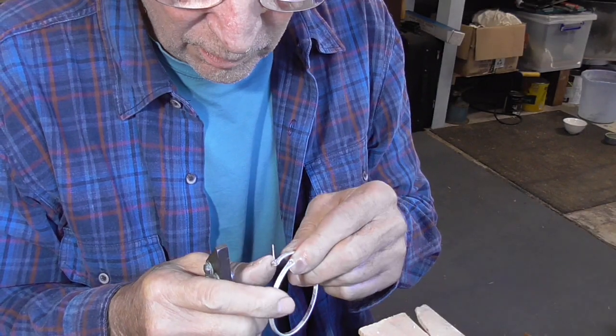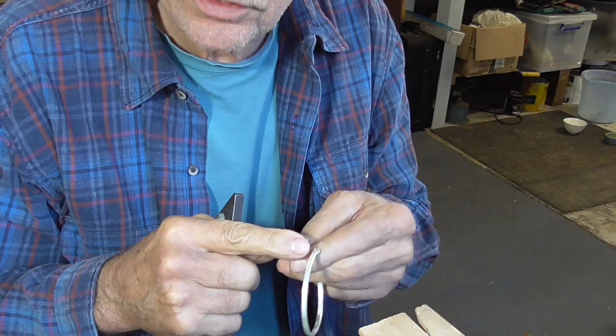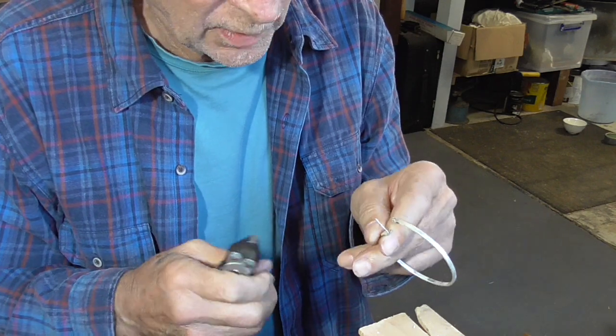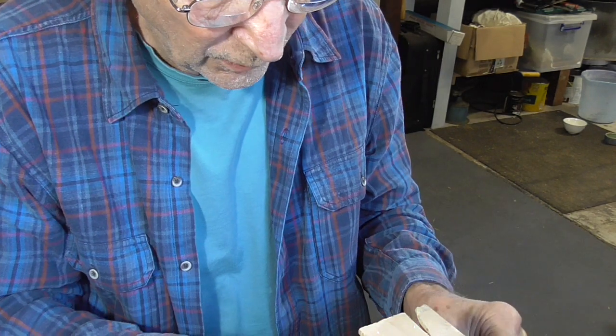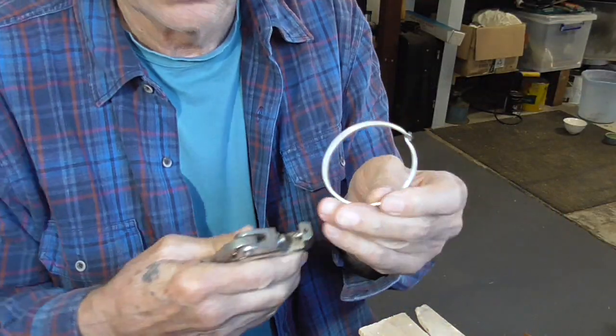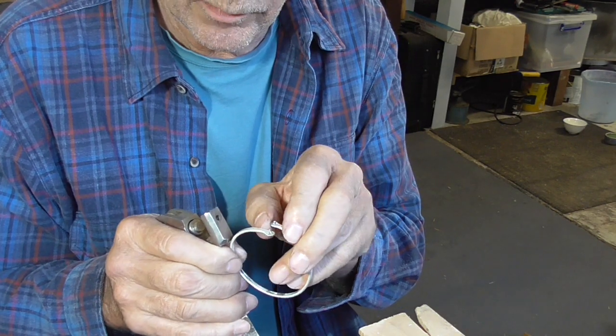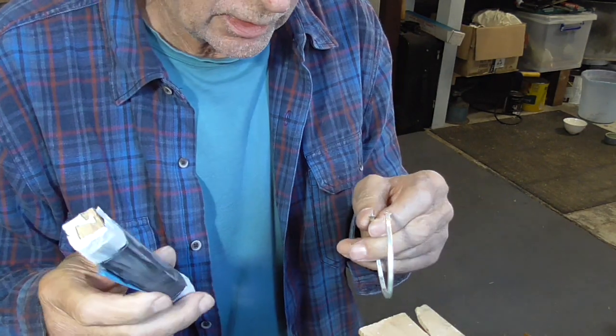After you've quenched this, check all of your solder joins, then pickle it. Twist your square wire — it doesn't have to be a really tight twist, as long as it's twisted. Half a turn is enough, though you can go a full turn if you want. Cut these to length, roughly two millimeters long. Hallmark it, and you're ready to polish. Polish it, check the ends, make sure they're nice and smooth — if they're not, sand them. I use 400 grade paper on a sanding stick.